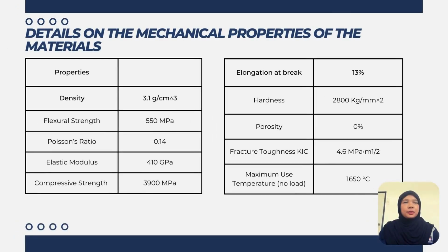Next, for the mechanical properties of the material. Silicon carbide has a density of 3.1 grams per centimeter cube, a flexural strength of 550 megapascal, the Poisson ratio is 0.14, and its elastic modulus is 410 gigapascal. These are just a few of the mechanical properties which describe silicon carbide as a material. So silicon carbide has a relatively high hardness of 9.5 on the Mohs scale of hardness. This is even harder than aluminum oxide.